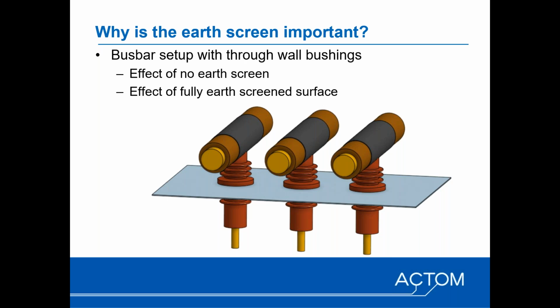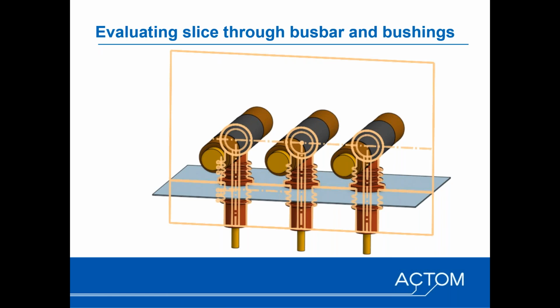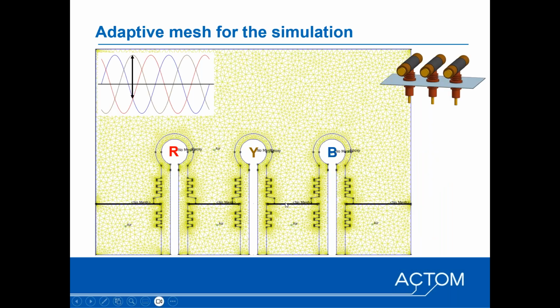To further illustrate the effect of the earth screen, I've got an example that I've done with a few field plots, where we looked at a bus bar setup supported through insulators, basically through wall bushings on a metal plate, and evaluated the field plot and the effect of the voltage with the bus bars screened and the insulator screened, and without the earth screen applied. If we take a slice through the setup, we get a 2D view of the bus bar setup, where we've got the 3 phases, the conductor running through the earth plate, which is in this location, and then insulators supporting the bus bars.